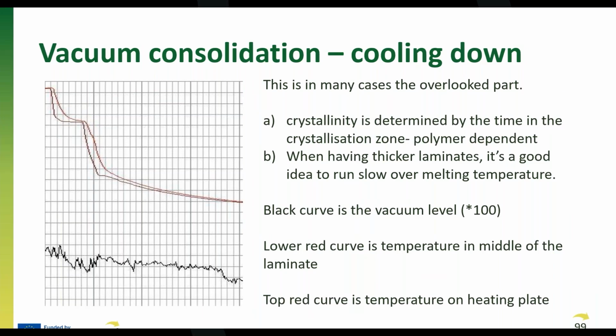But when you are having a thick laminate like this one, then it's also good to run over the melting point very slowly, so that you are actually getting a very uniform material throughout the solidifying process. So that's why you also see a kink like a shear in this one, where the melting point is, before we go down to those temperatures. And again, the vacuum level is constant at the bottom. That's very important. So thank you. Next one.